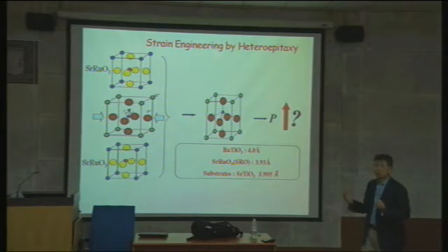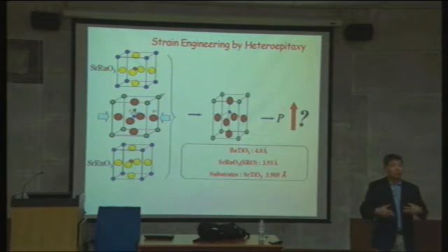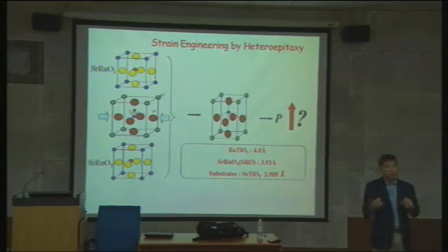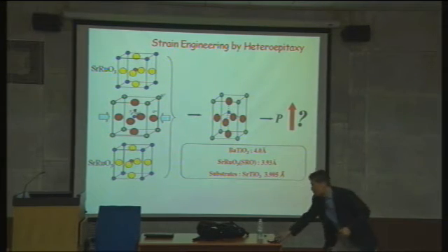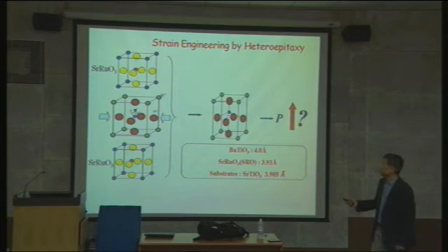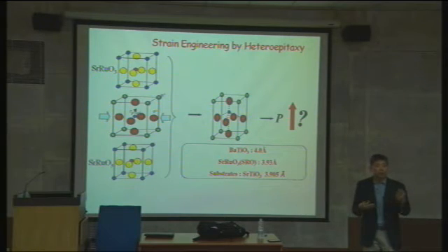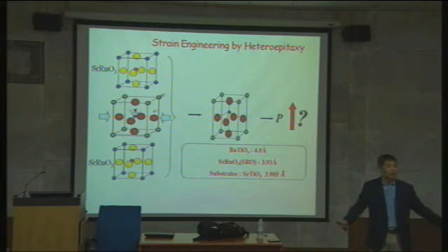The same thing. So here you can grow thinner, down to 2 angstrom, but that can be done only with an elemental source. If you have complex materials like a composite target, the minimum building block is 4 angstrom, because you provide A cation and B cation at the same time, so your building block cannot be 2 angstrom. You grow unit cell by unit cell, which means your growth building block is the unit cell. So when you look at all the step heights, they are roughly 4 angstrom. But if you can really control this layer and this layer separately, either strontium oxide or ruthenium oxide from separate sources, then you can make a 2 angstrom building block. So the minimum controlled thickness is 2 angstrom. Iron selenide is just a binary one, so it's one monolayer, which is basically single layer superconductivity.